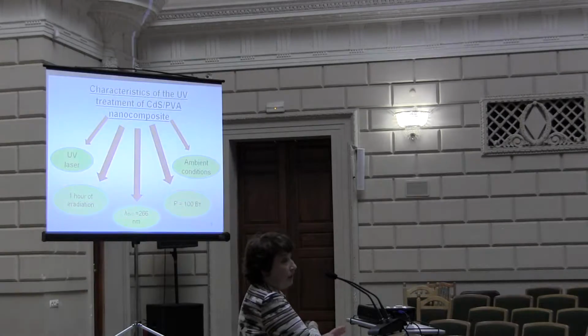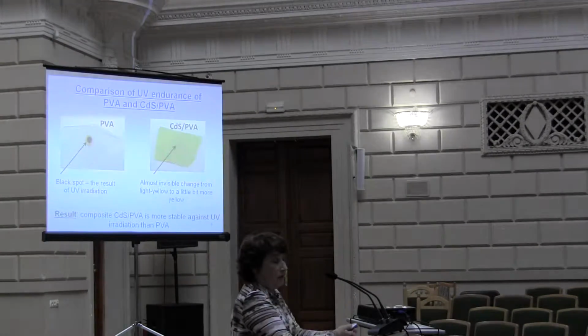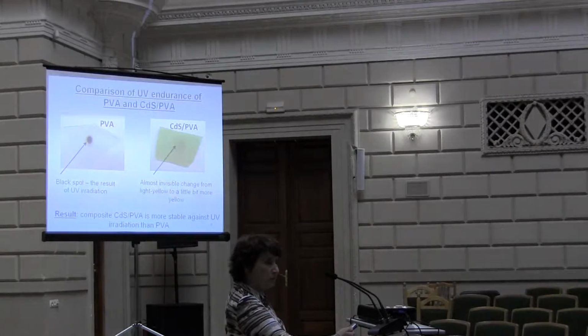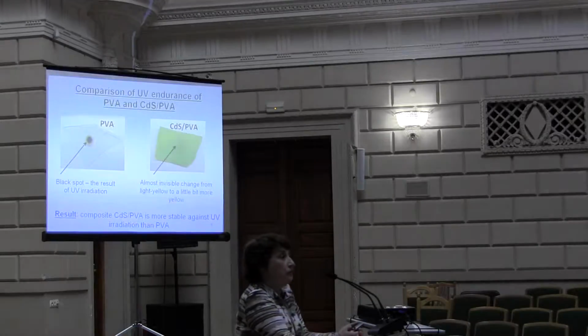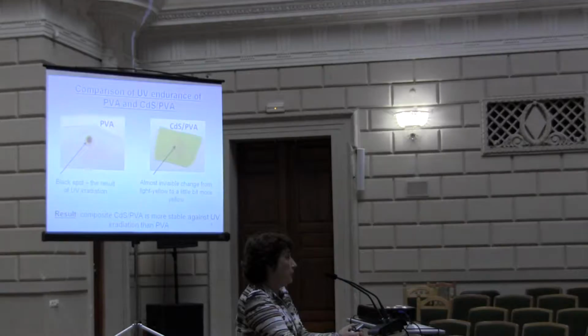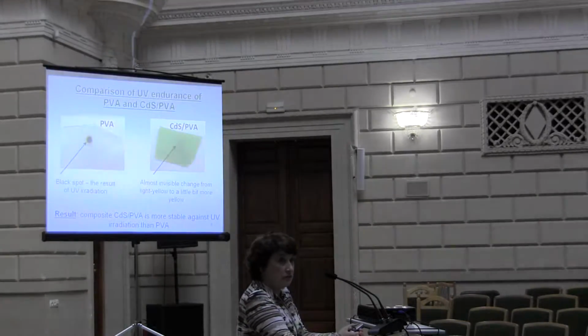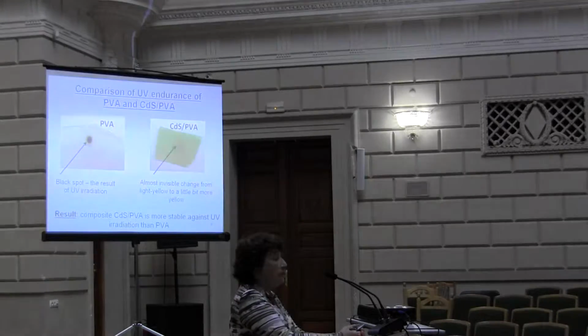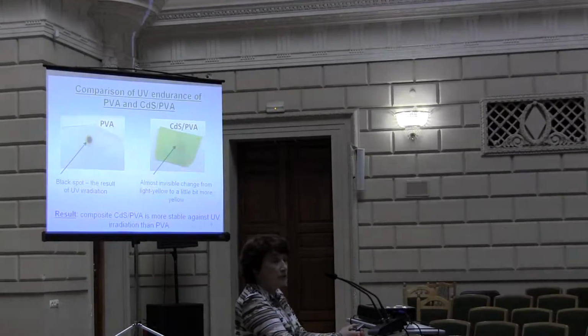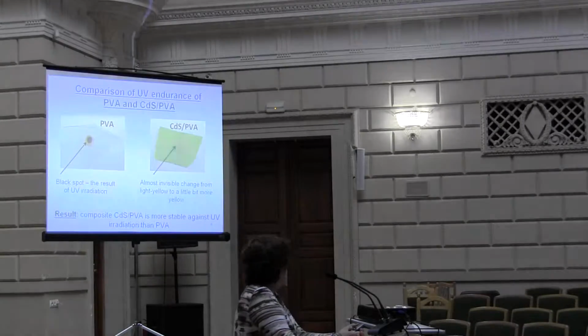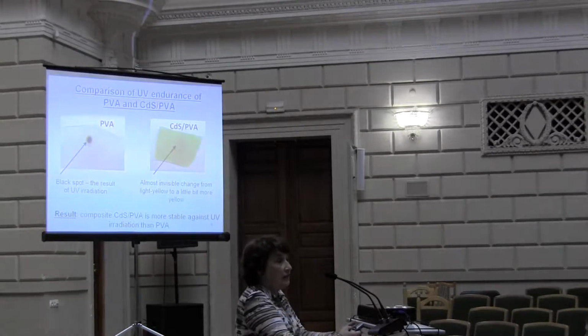The next slide will be the undeniable evidence that we achieved our aim. Here you can see the left panel from your side. The left panel is the photo of the pure polymer, and the black spot on it is the place where the laser beam hit the surface. You can see that the polymer is strongly damaged. The right panel is the photo of the nanocomposite subjected to the same exposure. As I can see from here, there is a little bit more yellowish spot, but it's not too easy to distinguish. So, this is a proof that we have protected our polymer from UV damage.